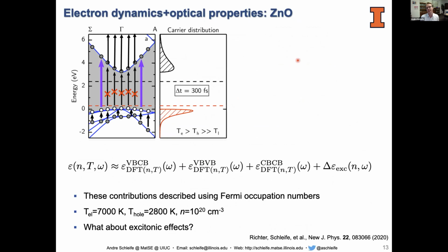And in that case, they looked at zinc oxide, which, as a material, has maybe been studied for a long time, but in their case, they used it because it is a very well understood material. And if you apply a new experimental technique like this time-resolved ellipsometry to it, it's nice to have some reference data to compare to. And their pump pulse created these excited carrier distributions. Okay, you can see here, excited electrons, kind of Fermi-like, excited holes, also Fermi-like, after 300 femtoseconds.